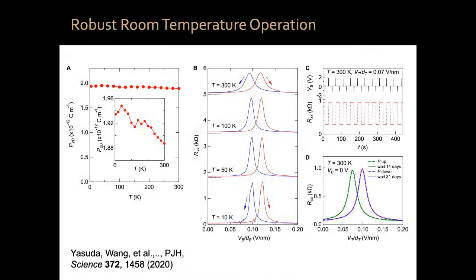It's about the only thing in my life I've done that works at room temperature. Usually I go, 4 Kelvin is high temperature for me typically, but this thing actually works at room temperature. So you can actually make a memory element out of this, and you can repeat it as many times as you want, etc. Even better, we've done this thing with hexagonal boron nitride, but if you think about it, the